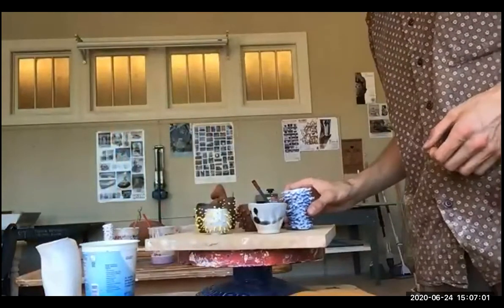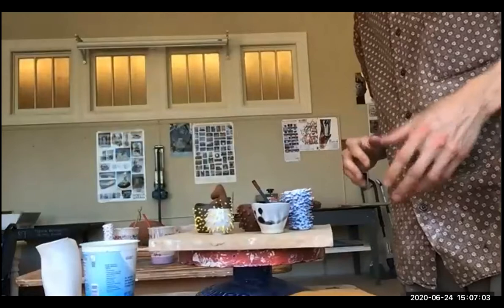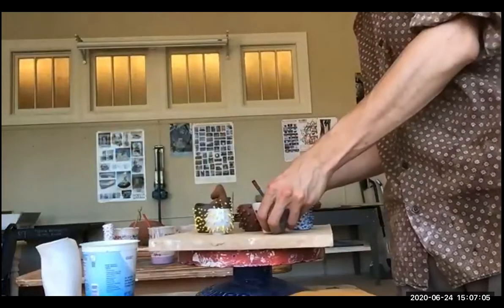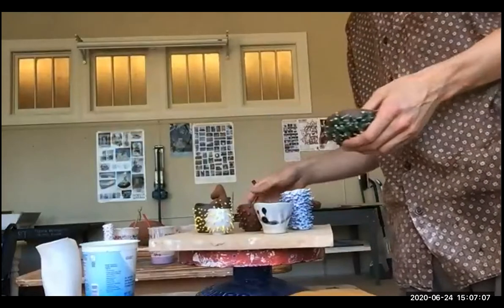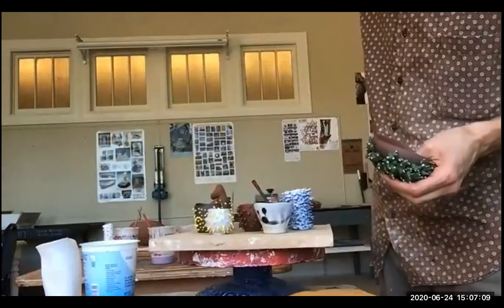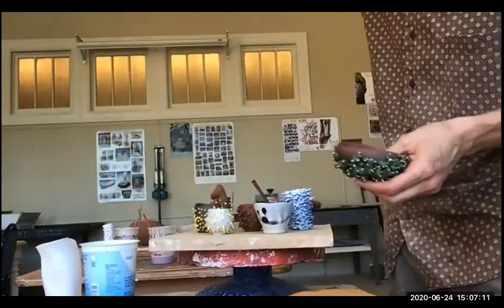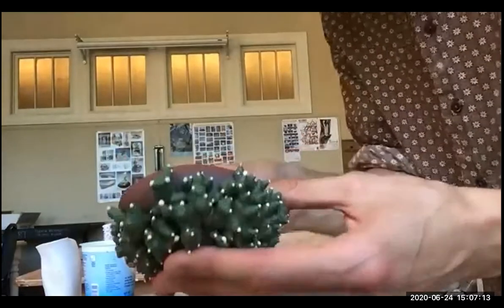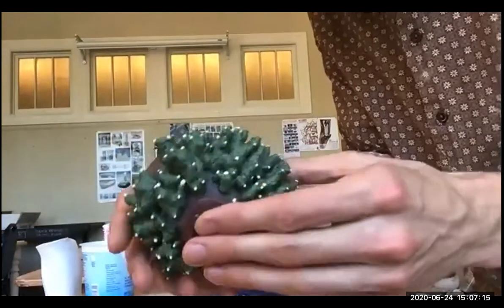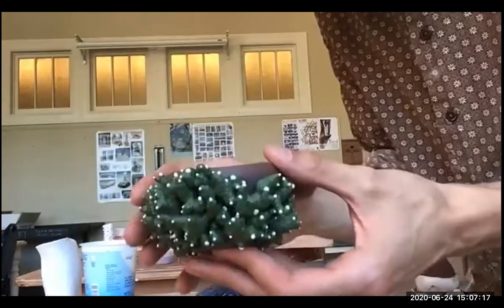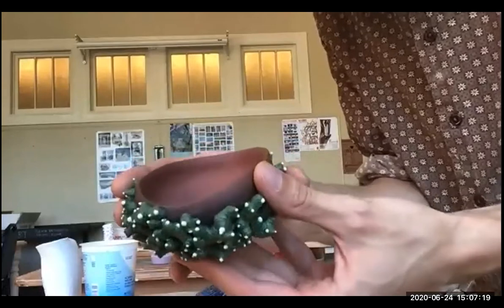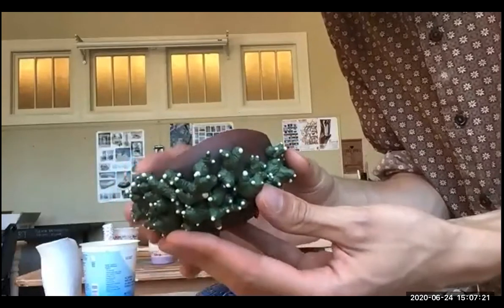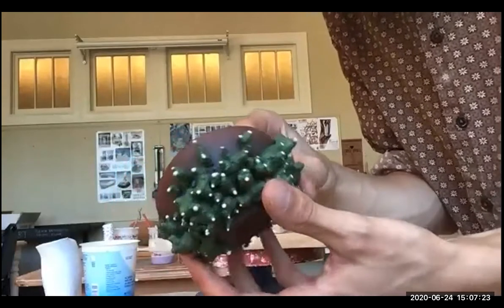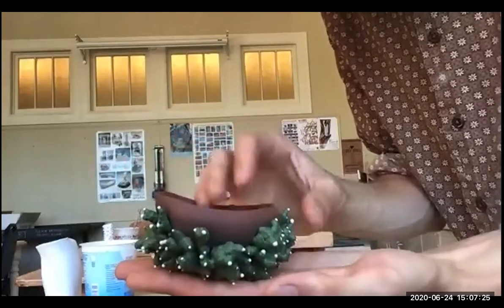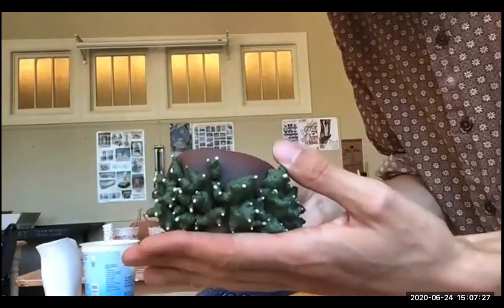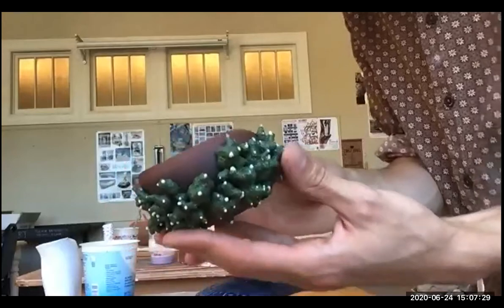So there are a bunch of different slips that I use in this vein. And frankly, they're not really slips. These glazes have about 5% clay, but I treat them as slips. This is a very similar recipe, but it has some silicon carbide in it, so it inflates. So it's built up in those same tendrils, but they just sort of puff up.